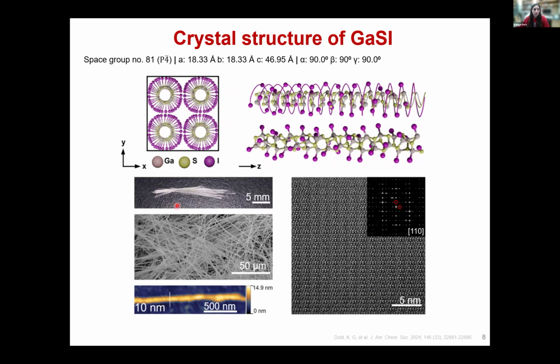Of course, again, we can grow these crystals very long, and these materials can also be exfoliated using Scotch tape into nanowires, where we have been able to find one that is only 11 chains thick of gallium sulfur iodide. These materials do retain their crystallinity at these size regimes, and we can see through high resolution transmission electron microscopy here that the helical motif is retained at the atomic scale.